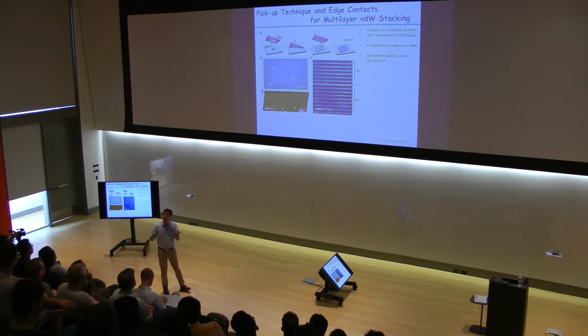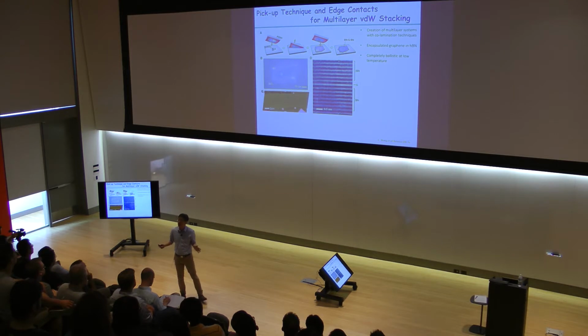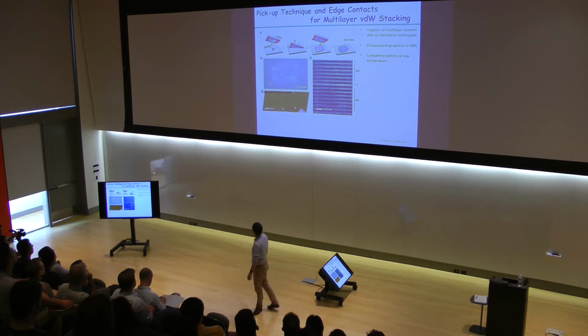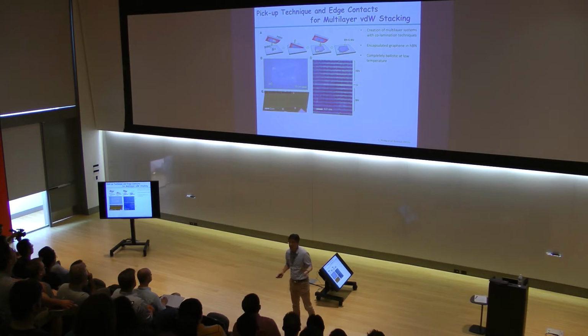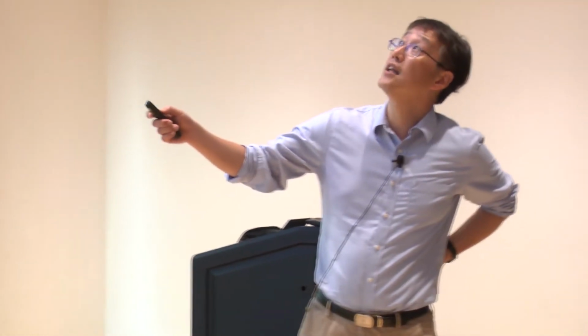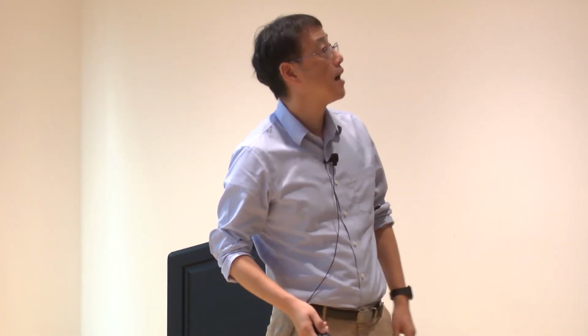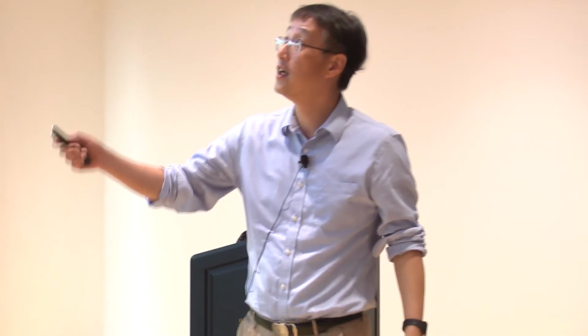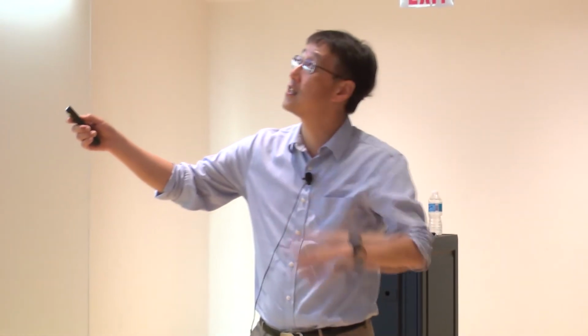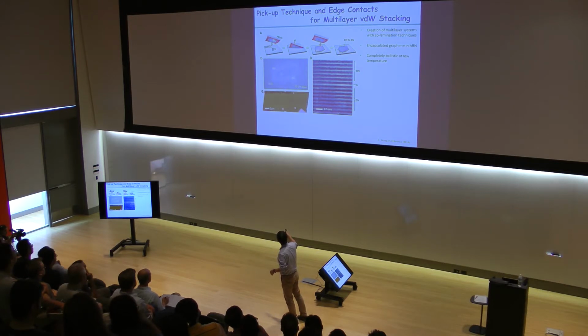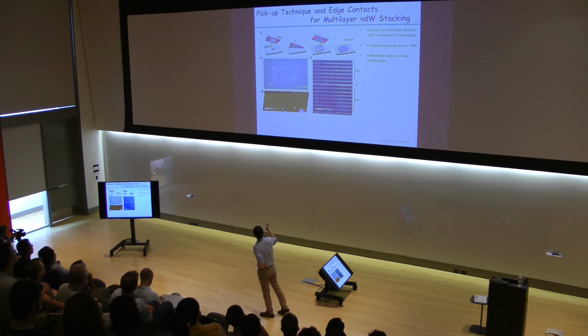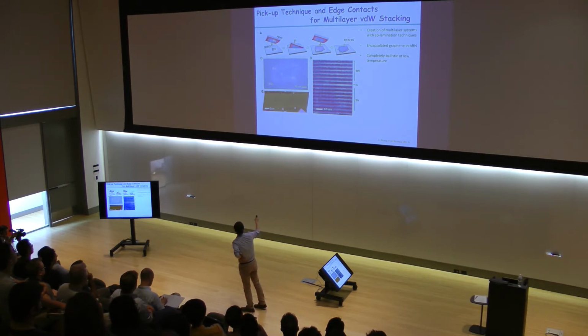But even before that, if you are not worried about scaling up, the following idea works quite well. I told you that we can cleave this material down to a single atomic layer on a surface, say a silicon oxide surface. Then you can prepare polymer tapes or a polymer membrane, specially designed such that it may not leave a lot of residue, and we can control the adhesion. Then you pick up the van der Waals system you want to start with. Typically, boron nitride is a good system because it is a good insulator. Then you bring this boron nitride down onto the single layer system, in this particular case, graphene. By changing the temperature of the substrate, controlling the adhesion between the silicon oxide and this material, and between the material and the boron nitride, you can controllably pick up these materials, say from the silicon oxide, and attach them to the boron nitride, right?